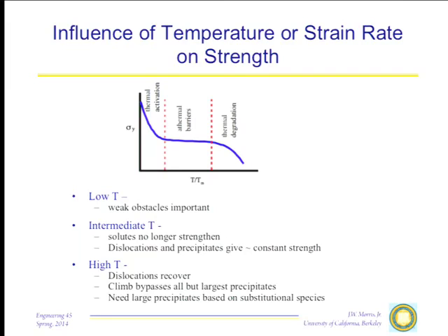What's happening here? Down here at low temperature, dislocations, like everything else, are in a medium that is undergoing thermal vibrations. So the dislocations vibrate, and the dislocations can activate past these obstacles. You can get past the obstacles by being physically forced through them, or you can get part of your activation from thermal excitations. Now, how hard it is to excite something past an obstacle depends in part on how big the obstacle is. If we're down here at very low temperature, solute atoms can be surprisingly effective. Maybe not great strengtheners, but there are a lot of them, but they're very small. It's easy for a dislocation to bypass a solute atom, or even to drag the solute atom along with it, if temperature gets to a significant value.